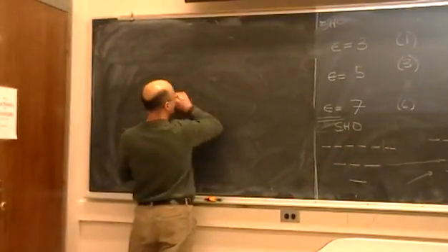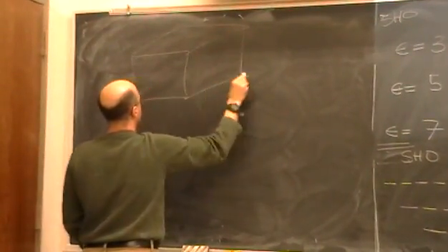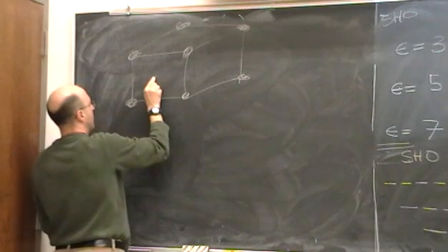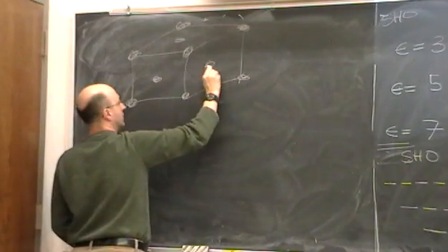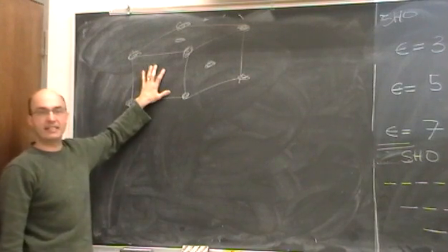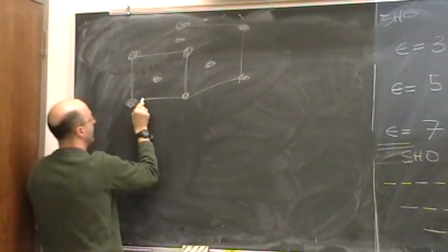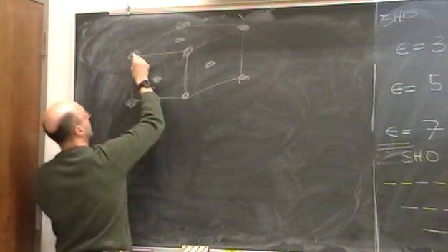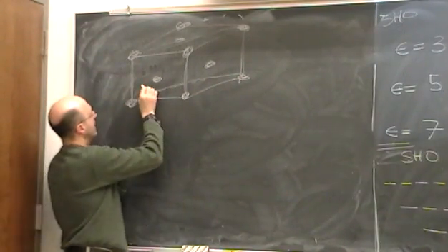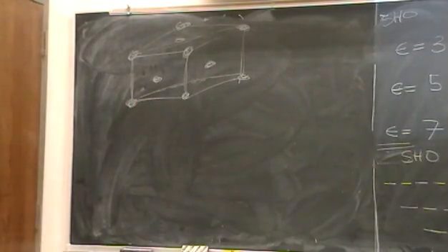So I'm going to show you the electron density in germanium. The crystal looks kind of like this. There's a cubic cell that we've calculated with. And it's FCC, so you've got all the corners of your cube, and then you have all the face centers also. And then there's additional structure in the diamond lattice where there are atoms that are off this plane. So what I'm going to show you are the charge density sliced through this plane, the FCC face, and then through a diagonal plane that looks like this, through the crystal like so. And in that diagonal plane, you can actually see the atom to which the corner atoms are bonded. Because I want to see what the bonds look like also. Ah, there you are.